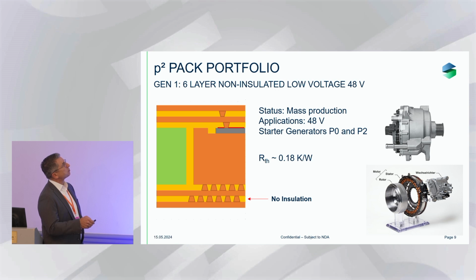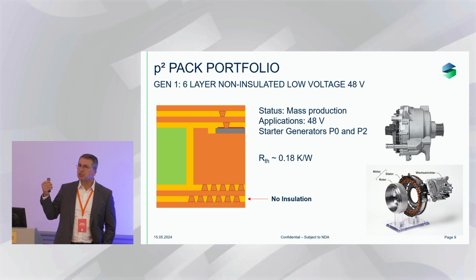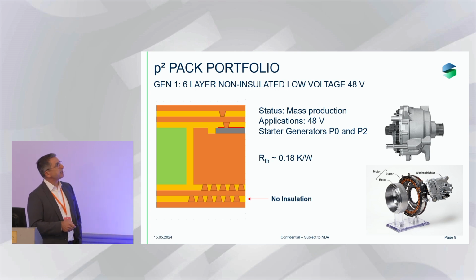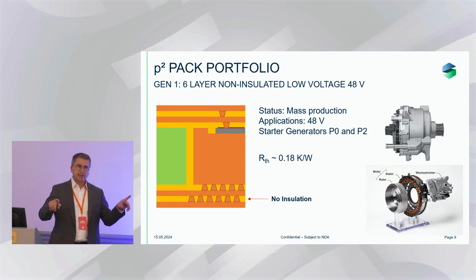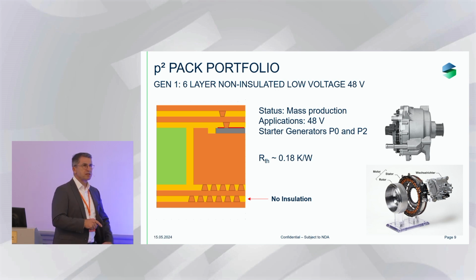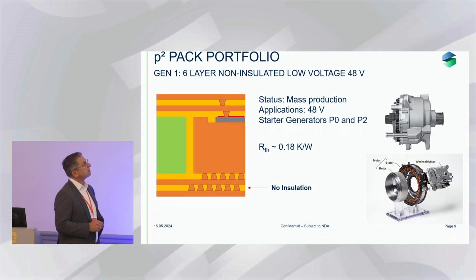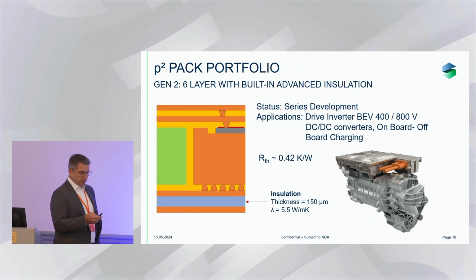So the total thermal resistance from the junction to the outside, so somehow junction to case, is in the range of 0.2 kelvins per watt per die. If you do parallelizing, the module resistance will drop. But if you now go for insulated version, you see what happens.